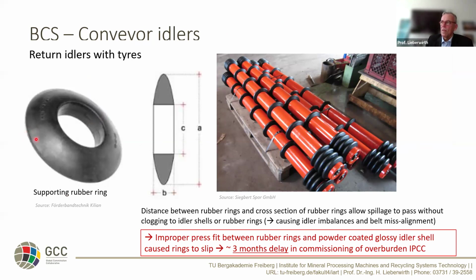Another point, the rubber rings: the lower strand idlers look easy. You have just these idlers with the rubber rings to allow the spillage to pass through. You don't have buildup on the idlers. Everything nice and shiny. I had an issue which caused 3 months of delay in the commissioning of the system, a 4 kilometer in-pit crushing and conveying system. Idlers manufactured or bought by a well-reputed American brand. They manufactured them in China. Everything would look nice, even better than those here. So the surface was glossy, it was powder coated.